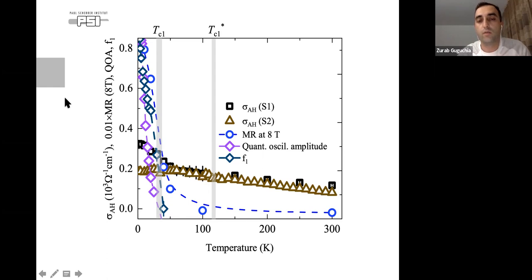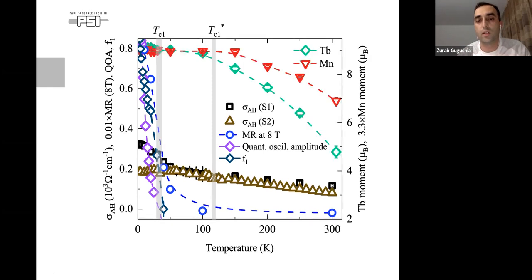So after that, we thought, okay, can we really tune these different patches or domains with hydrostatic pressure? So one important aspect here is if you measure the moment size of the terbium manganese, there's not much influence. Okay, it's saturated because I think we get the static regime. So this anomalous Hall conductivity is not really influenced by the moment size, but it's more influenced by this magnetic crossover at low temperatures. And this distinct behavior here can probably be explained by distinct magnetic domain distribution, which can be created by different cooling of the sample and so on, combined with magnetostriction.